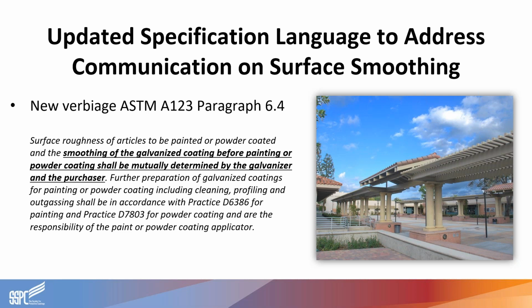This new verbiage highlights the need for that mutual agreement between the galvanizer and the purchaser, which is really important because not all galvanizers may have the capability to perform all of the surface smoothing at their facility. And at the same time, not all painters are expecting to incorporate all the steps for surface smoothing into their project bid. So similar verbiage was also included in those surface preparation standards, ASTM D6386 for painting and D7803 for powder coating. And that was done recently, in 2019.